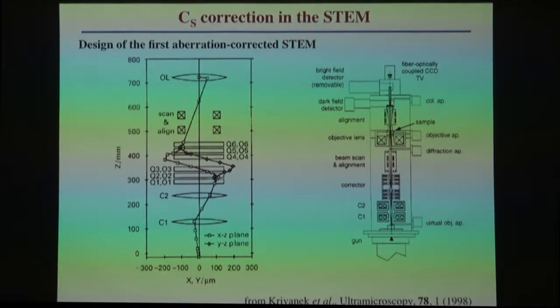Well, traditionally they say whatever you can do in TEM, you can do in STEM. And Krivanek and colleagues were able to show CS correction in the STEM. They started off by using a VG microscope with a field emission gun. The electron gun is at the bottom of the microscope, and they have two condenser lenses, then an octopole, quadrupole, quite a complicated system compared to the simple two hexapoles, but nevertheless you can build this corrector element, and they were able to put it into the column of the VG HB501 in Cambridge, the first microscope.